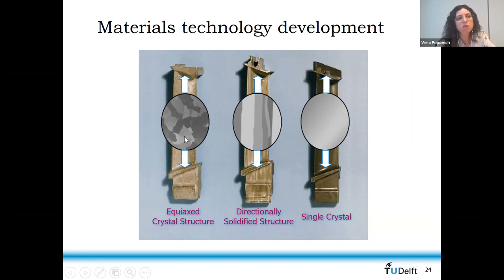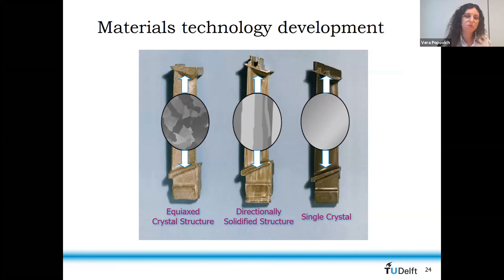And for creep resistance, this is not the structure that you would like to have in your material, because the creep mechanism, as we will cover in the next slide, is accompanied by grain boundary sliding. So the more grain boundaries you have, the more deformation and possibilities for sliding there are. So the more permanent deformation your material can experience, among other things for sure. So that's why